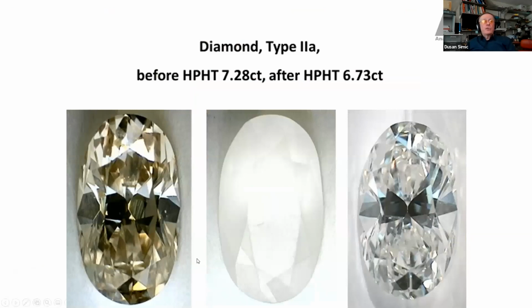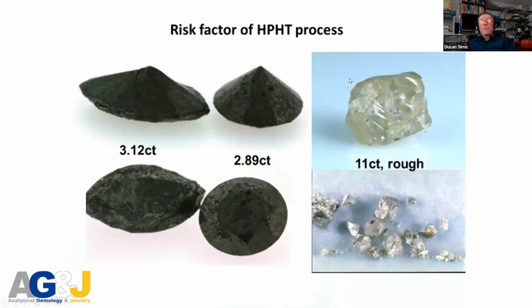And how it looks: this is a stone before treatment. This is the stone after treatment. The surface is, of course, damaged. This is a slight graphitization, and after polishing, we will get a significantly higher color. This is an FE color, and we lost about half a color for this stone, from 7.28 to 6.73.